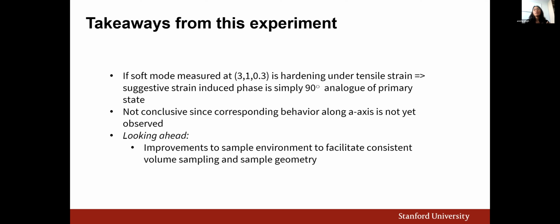So really looking ahead, what we're interested in is how we can improve this sample environment and also sample quality, things that we can do to still maintain robust strain of our sample while maintaining sample crystallinity. And then what changes can we make to how this sample is mounted within the strain cell to increase the angular access to our sample, so we could actually perform measurements along both in-plane directions in a single sample. And also things that we can do to more reliably maintain consistent sampling of our crystal volume. These are all things that we have to think about, particularly in how the sample is prepared and mounted, to better perform these experiments in the future. Yeah, so that's all I have for now. Thank you, and I'm happy to take any questions.